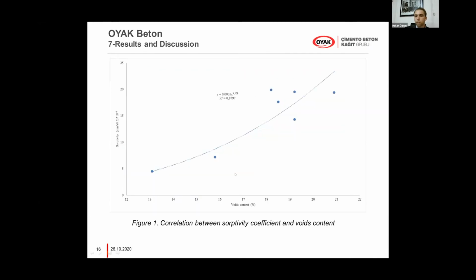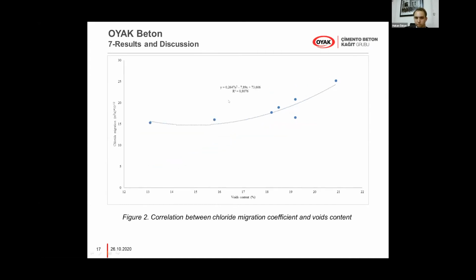And also, of course, we can say that void content has a good correlation, a good relationship with sorptivity, and the correlation coefficient is 0.88. And we can see a similar correlation between void content and chloride migration, 0.81.